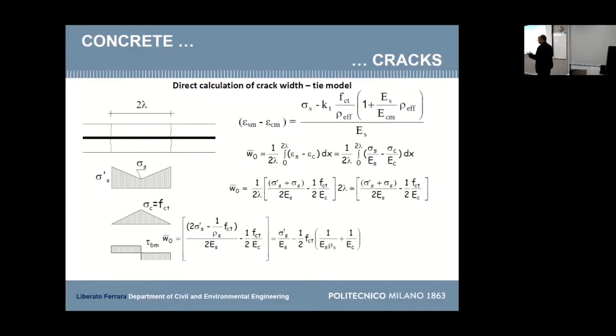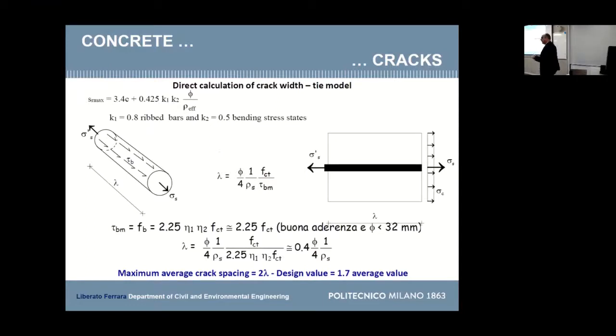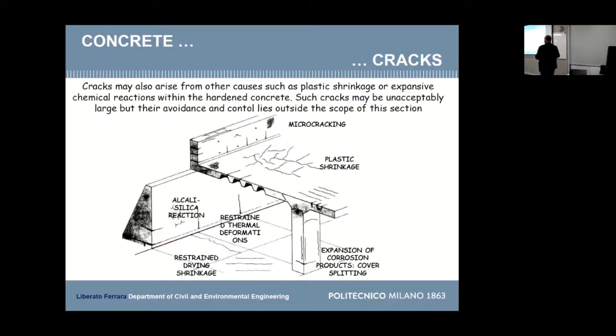So we calculate total crack width as the unit crack width, the difference in strain between steel and concrete, which you can work out from any handbook, multiplied by this length parameter. So this means that if you have smaller bar diameters, you will have more cracks, but each one of them will be smaller. And this is good from the structural point of view, because the crack width is the parameter which governs the durability, but it also governs the loss of stiffness, which impairs the serviceability, for example, the deflection of the structure.